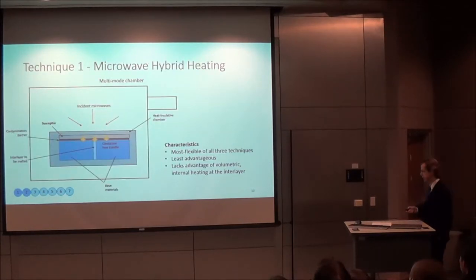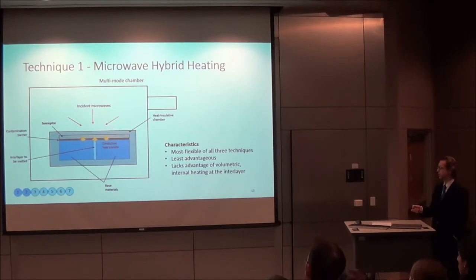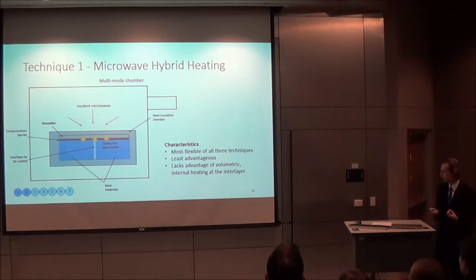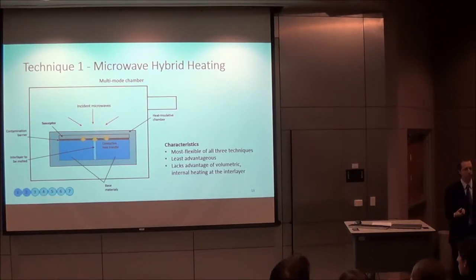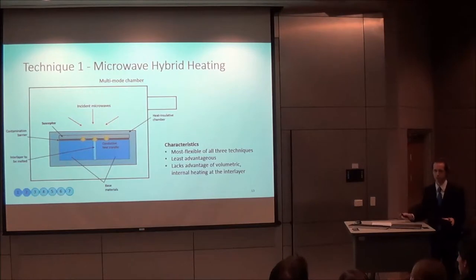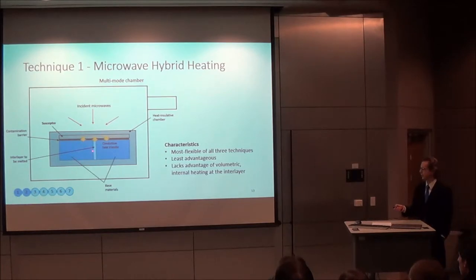So technique one can be illustrated thus. Usually it's performed with a multi-mode chamber, and there is some heat insulated chamber in which the joint is placed, and a susceptor external to the joint that will absorb microwave energy. The base materials may be highly reflective to microwaves, for instance, metals. This is the only technique that's used to join metals to metals using microwaves. And the interlayer, if it's some kind of brazing or soldering process where the joint materials may not be melted, is heated, and the heat is transferred to it from the susceptor, but not directly from the microwave-material interaction. So it's generated in the susceptor and transferred to the joint.